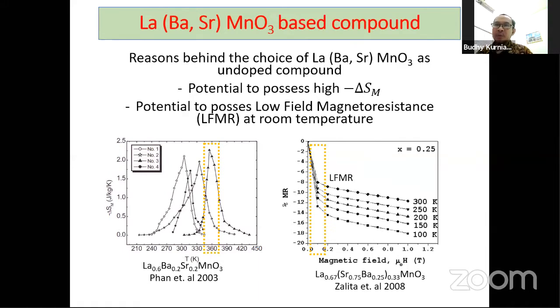And also, we found that in this sample, for the magnetoresistance phenomena, there is also low field magnetoresistance. So this kind of unique characteristic of the sample gave us the intention to develop and to explore some of the physical properties in this material. Next, please.